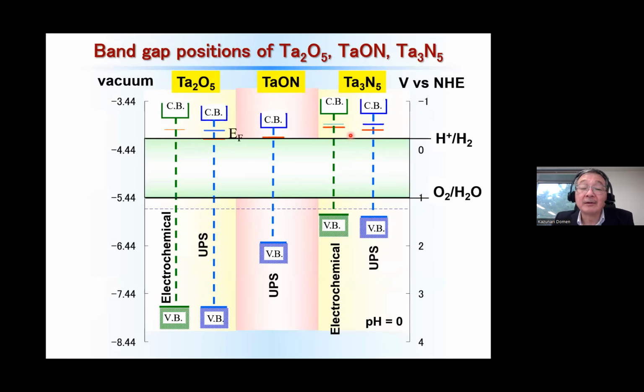We also examined the band gap position of these materials by electrochemical method as well as UPS. In this case, only UPS was available. If we compare the conduction band minimum, even when we carry out the nitridation, the conduction band minimum was almost unchanged. On the other hand, the valence band maximum shifts up with increasing nitridation. However, even in the case of Ta3N5, these materials still have a suitable band gap position to split water into hydrogen and oxygen.